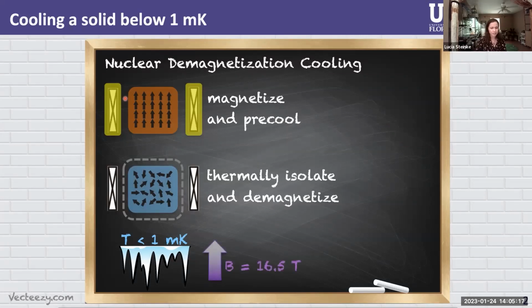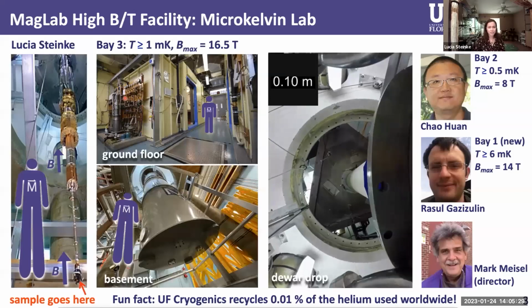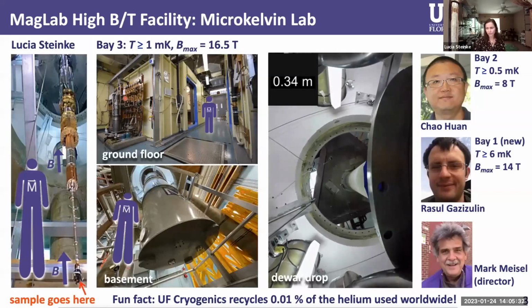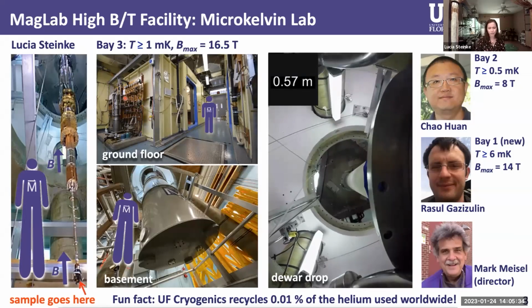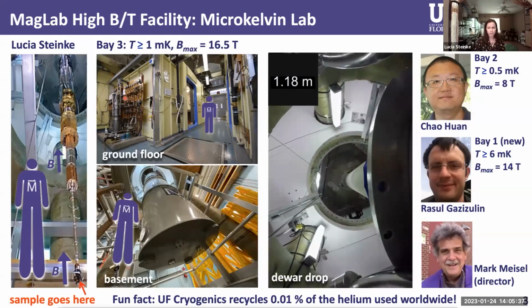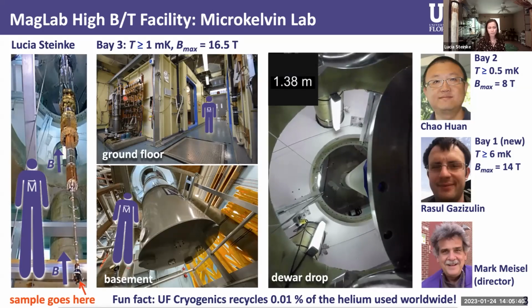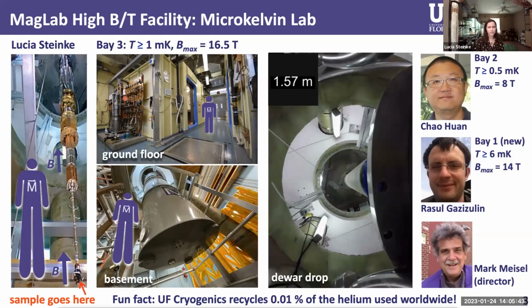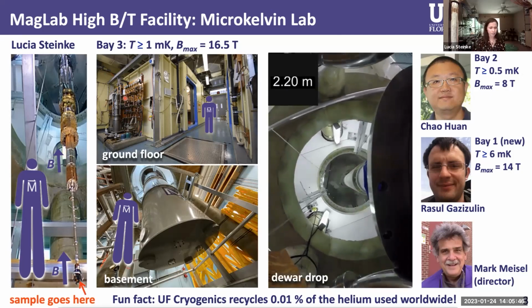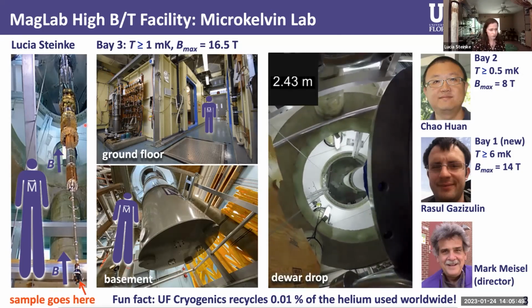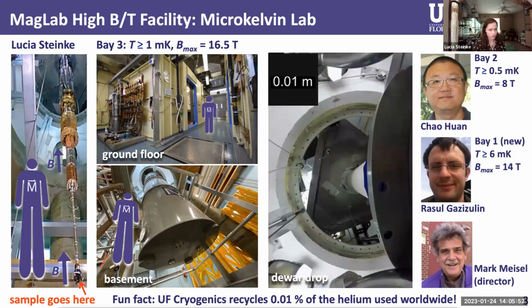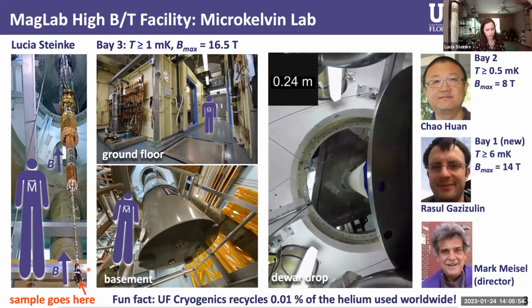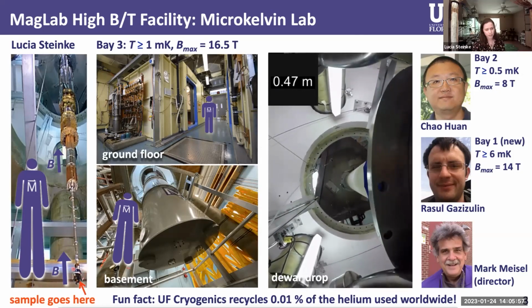And now our specialty is that we combine these ultra low temperatures with high magnetic fields up to 16.5 Tesla. This is what that looks like on a chalkboard. So let me show you what that looks like in real life. Here's an image gallery showing our microkelvin lab of the High B over T facility. Apart from Mark and myself, we have two more permanent staff scientists working there. Chao Huan is mostly responsible for the Bay 2 cryostat. Rasul Gazizulin has recently set up a brand new cryostat in Bay 1. And I'm mostly working on Bay 3, which you see out in the open here. So that's our nuclear cooling stage where we apply one magnetic field. And then at the bottom of a long cold finger is where you find our sample. And this is where we have a second magnet for the experiment.